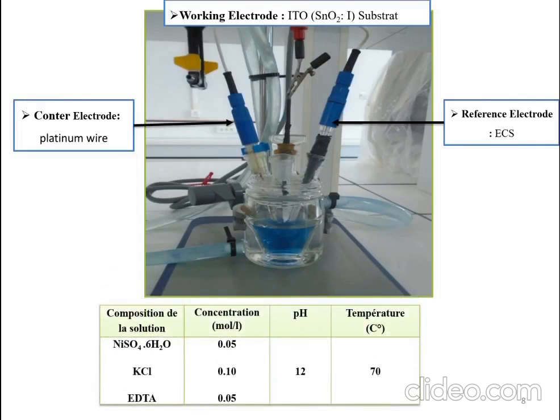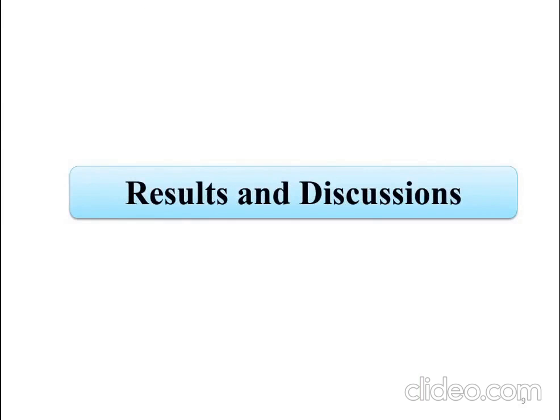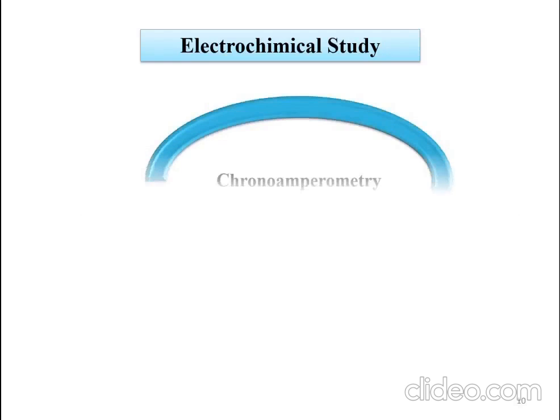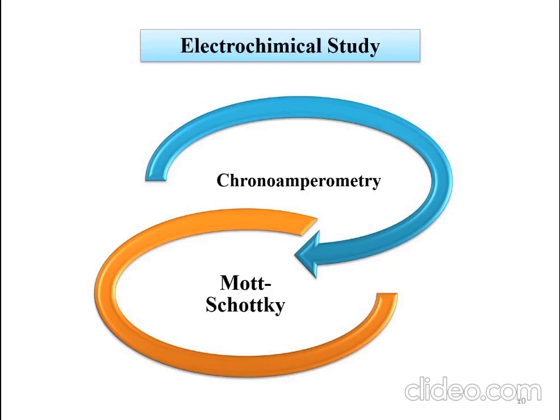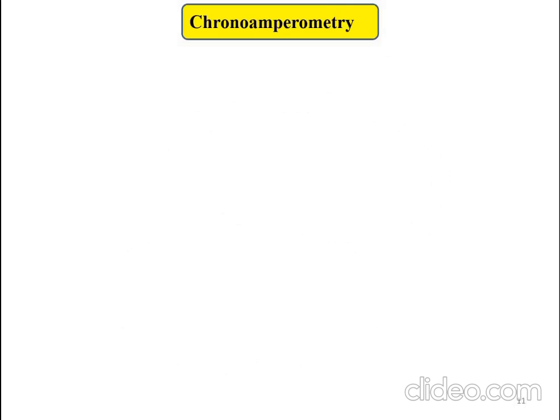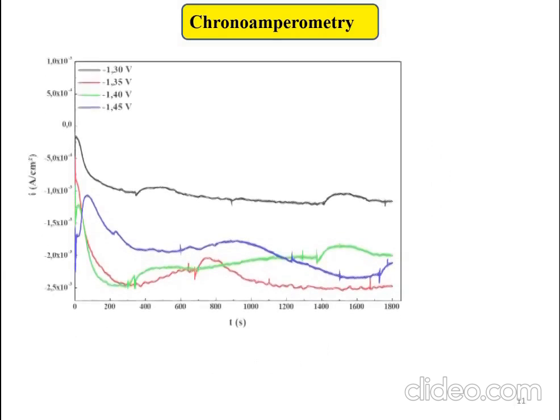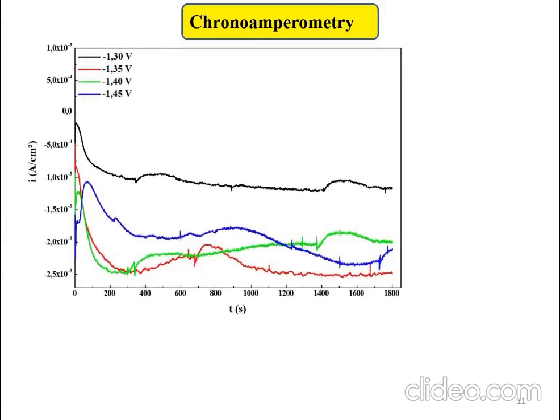Putting all those chemicals together, we will have a pH equal to 12. The temperature of the solution was fixed at 70 degrees. For the results and discussion section, two main parts will be presented. The first part is the electrochemical study, which included chronoamperometry and Mott-Schottky measurements. The chronoamperometry was used to deposit our thin films of nickel oxide on the ITO glass substrate.